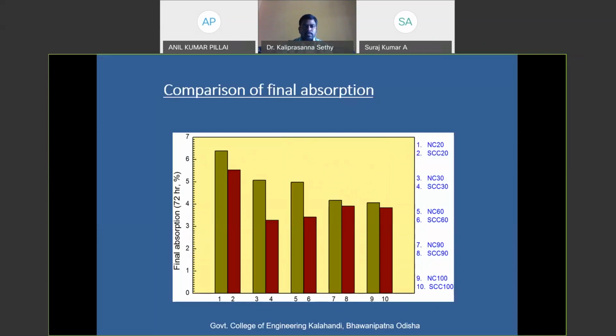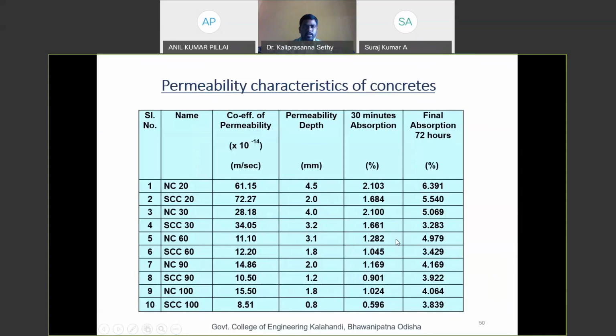And this is the comparison of final absorption, plotted for 72 hours. So at 72 hours, we get a maximum of 6.5 percent absorption value for NC20 grade concrete. Here is the table for all those characteristics which we have found in the earlier slides.